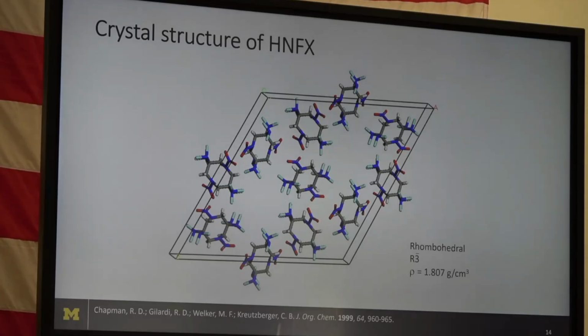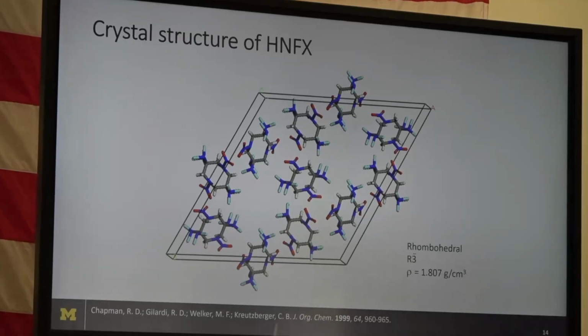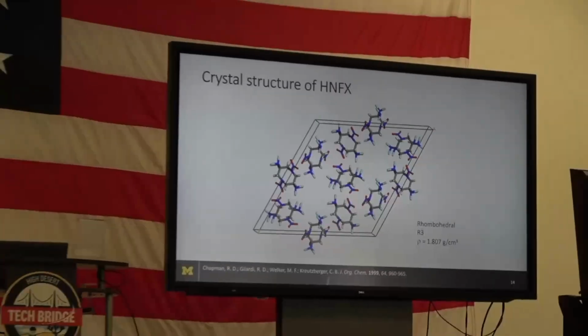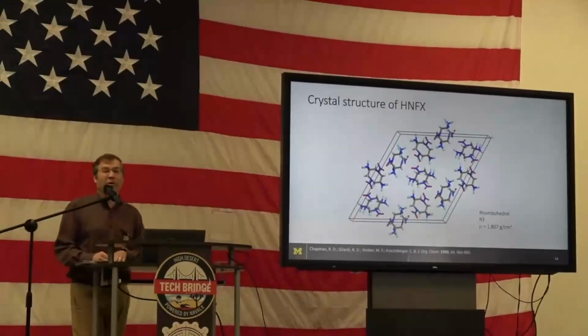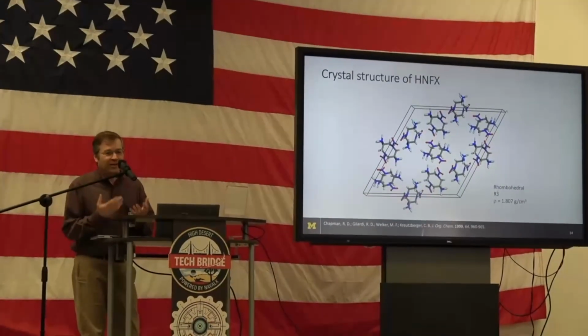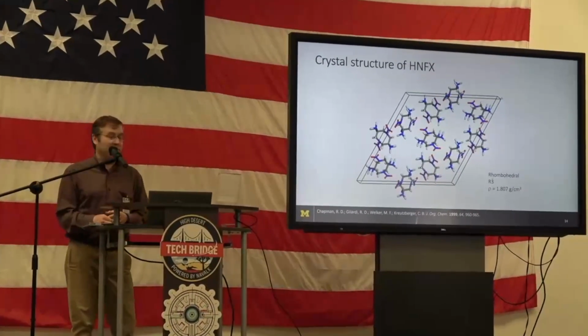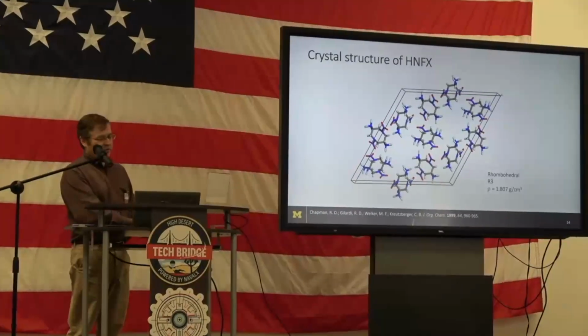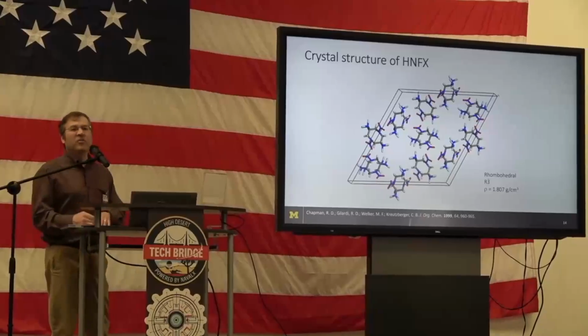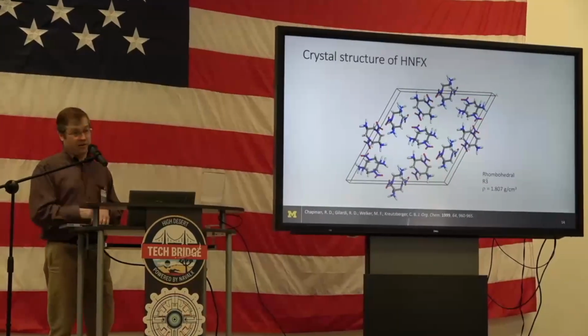And so here is the crystal structure of HNFX. The crystal structure is correct. It's been determined a couple of times by us and by other people. And it has a property you don't see very often in organic molecules, which is it's got a hole in the center. And in fact, this hole is big enough you could put hydrogen in there. We've done hydrogen absorption measurements, and you can stuff that into there. So this is just happening to crystallize in sort of an unfortunate, from an energetic standpoint, manner where it has some porosity in the structure, and so it gives us a density that, while okay, is nowhere near what it should be predicted from the structure.